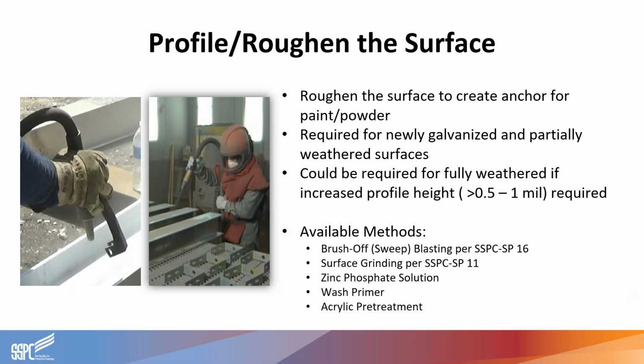Next, most galvanized surfaces will need to be roughened to promote adhesion of the coating that's going to be applied. Although weathered galvanizing is known to have some natural roughness that can be painted over without additional roughening, if you're applying an industrial or marine grade coating, or a coating that has significant peak height or roughness requirements, that may not be sufficient to paint over as is. So regardless, this is where the specifier needs to step in and clarify whether you're dealing with newly, partially, or fully weathered galvanizing.